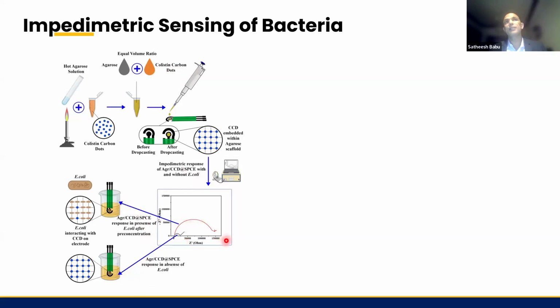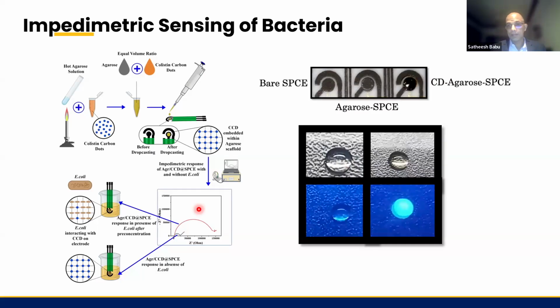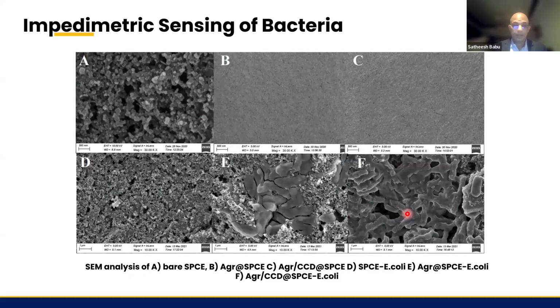Then we run the impedance spectrum. By looking at the impedance value, we were able to quantify the amount of bacteria present in the solution. And you can see once we modify the electrode surface with the colistin carbon dot, we could see the fluorescence of the carbon dot. That is a visual proof for the carbon dot on the electrode surface. And these SEM images show the various stages and how they interact with the bacterial solution.